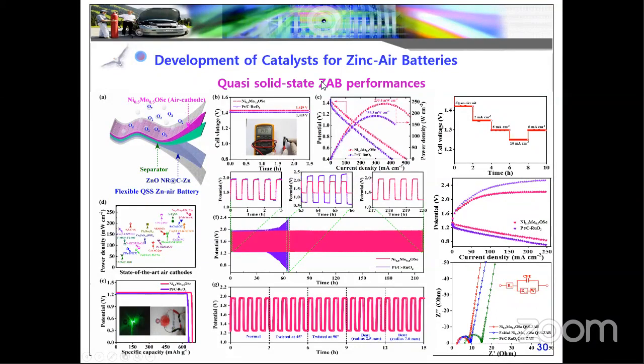When we fabricate the electrodes, the nickel molybdenum oxide is the air cathode, and zinc rod directly grown over the carbon cloth acts as the anode material, in order to avoid the corrosion effects of the zinc. Another advantage of zinc directly grown on carbon is that we avoid binders, especially polymer binders, because the direct growth method avoids binders and reduces the dead mass. And when we grow on carbon cloth, we can use it as a flexible and wearable energy storage device. We also compared these materials with the commercially available platinum, carbon, and ruthenium oxide couples.